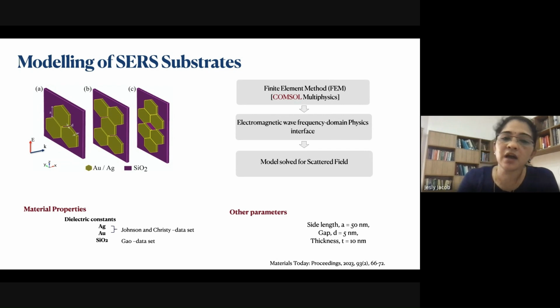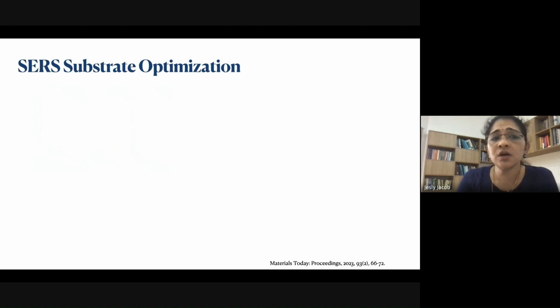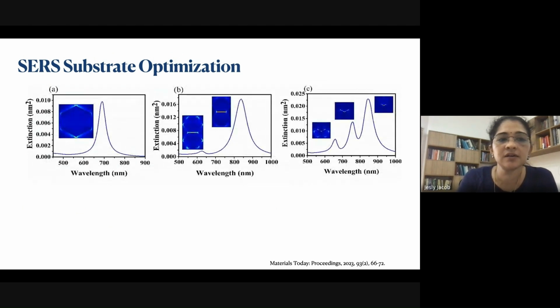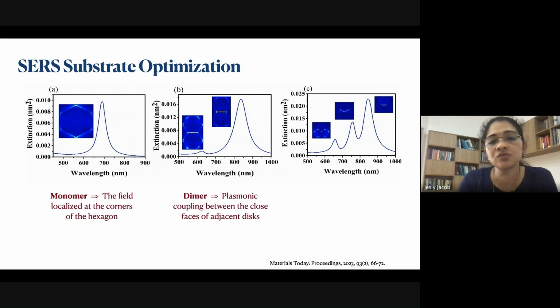Other parameters which we have used to optimize this trimer structure are that the side length of this hexagonal nanodisk is fixed at 50 nanometer, the gap D equal to 5 nanometer, and the thickness about 10 nanometer. So we will just discuss the SERS substrate optimization. First we have taken a monomer of hexagonal nanodisk, and we have taken the extinction spectra. You can see that here a hot spot is formed at the corners, and this results in the extinction spectrum. And next we move on to dimer structures.